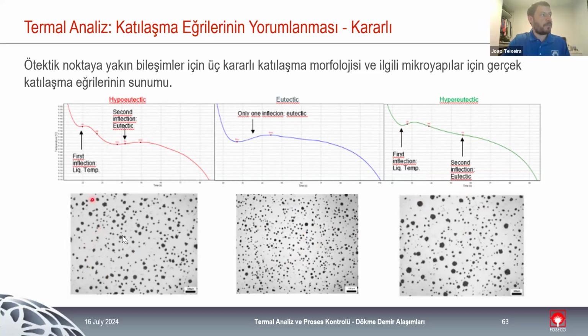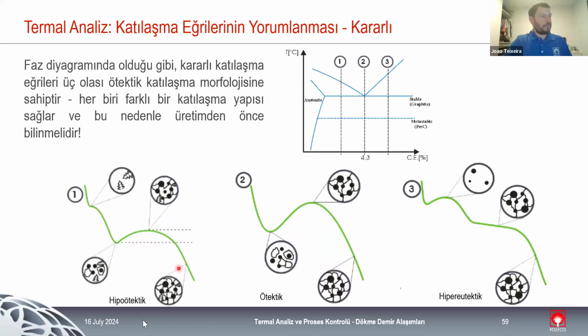The main difference between hypo and eutectic is, in this case, the nodule density. We have more nodule density at the eutectic phase because it happens in a single area, and it's not a mix of different points where the solidification of graphite happens. So we have a higher amount of nodules being formed in a single phase.